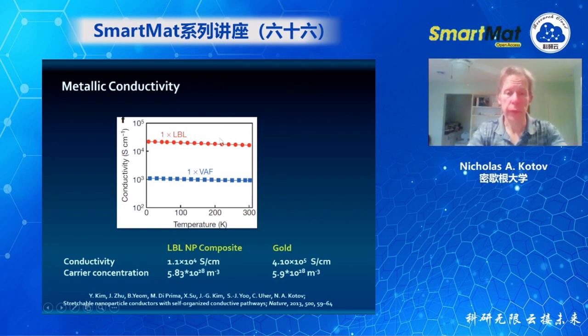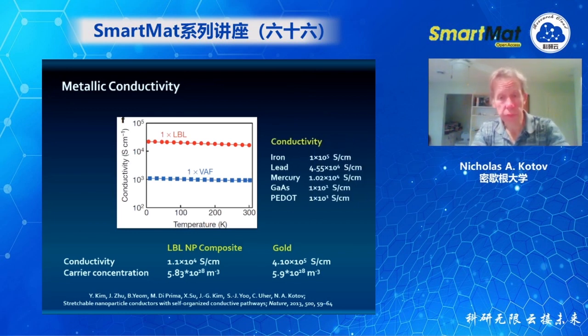In fact, if we look at the comparison with some of the vacuum-assisted filtration composites, so when you take, say, some nanoparticles, gold or clay or graphene, and under vacuum, you compress them on the filter. In this case, that gradual organization build-up of the layers results in much higher electron transport. In fact, we can compete not only with some composites, but also with some metals. In fact, the conductivity of these composites is actually higher than some of the ionic materials, and interestingly enough, is higher than in mercury.